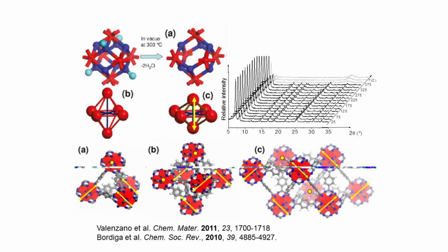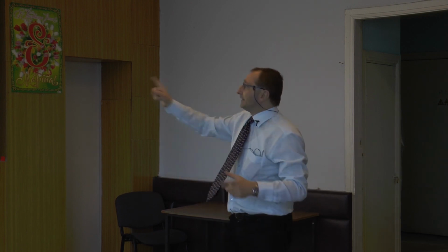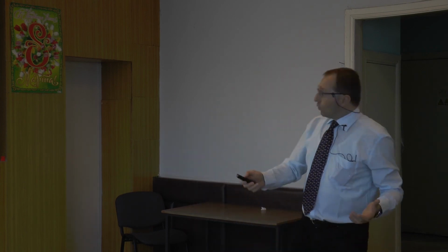What does it mean, random? Each octahedron has 3 diagonals. If all octahedra had been squeezed along the same diagonal, then this would have been an ordered squeezing, and this would have been seen by X-ray diffraction, which looks at the long-range order only. But if this is random, there is no long-range order, and X-ray diffraction just sees an increase of the thermal ellipsoids, but is not able to see what a local structure probe like EXAFS is able to see.